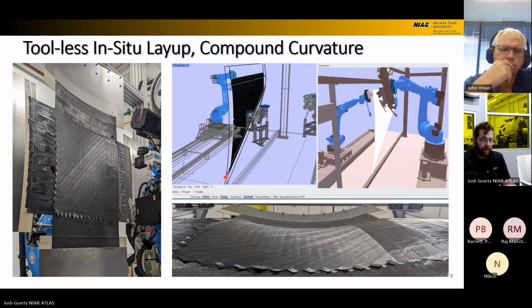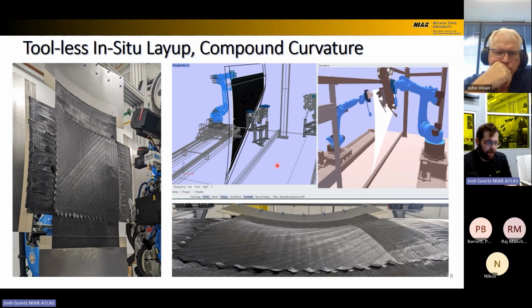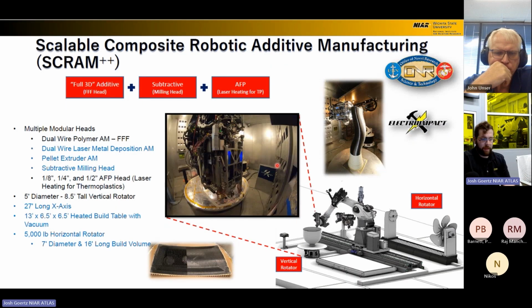And then any small deviations in the profile geometry of that part, we can deflect out of the part by attaching it to a fixed egg crate backing structure. So that was the toolless in-situ layup.